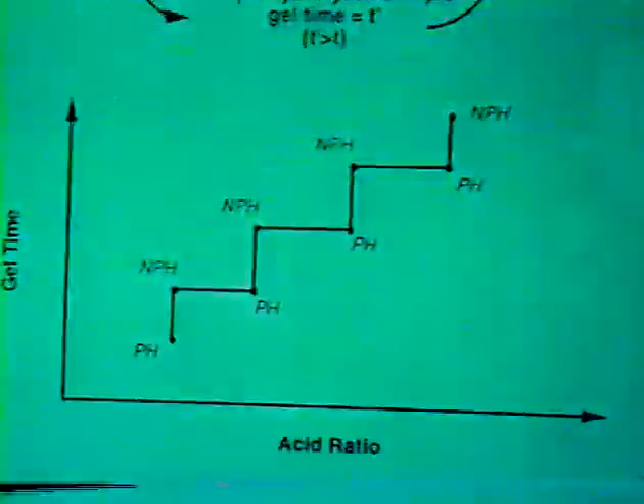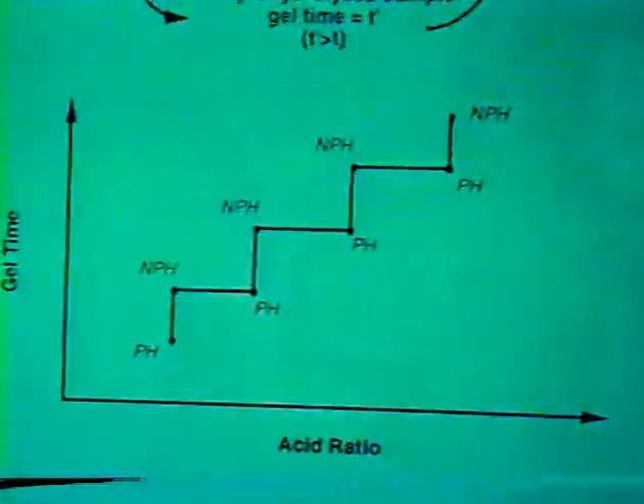We approach this synthesis by doing two series of samples, the non-prehydrolyzed series, in which we basically mix everything together, versus the prehydrolyzed series, in which the silica precursor is allowed to react with water for 10 minutes prior to the addition of the zirconia alkoxide. Now, having identified gel time as an important parameter in the zirconia world, we have to come up with a scheme by which we can isolate the effect of prehydrolysis from the effect of gel time. And this is accomplished by the following scheme. We have the following experimental design.